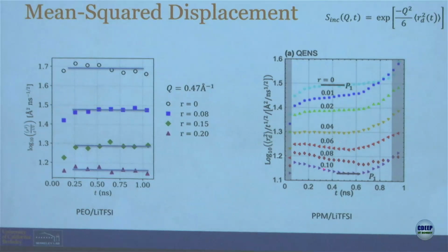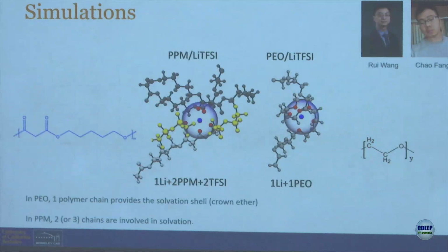When you go to PPM, a very strange thing is seen. You see a plateau, but at the highest salt concentration, this goes as a slower power than t to the half, then settles down, and then becomes something else. So this trough is something that we thought about for a little bit. Why is this happening? And that's when we turned to simulations.